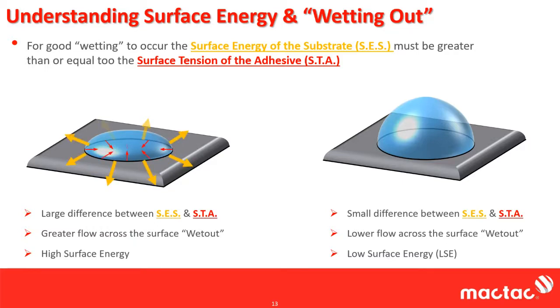On the right, then, we have an example where the surface tension of the adhesive is much greater than the surface energy of the material fighting to hold it, or I'm sorry, I'm saying this in reverse. The surface tension of the adhesive is really holding the bead together much stronger than what the surface energy of the material is trying to stretch it out. In this case, there's a much smaller difference between the surface energy of the substrate and the surface tension of the adhesive. What that results in is a lower flow across the surface, or you don't get as much wet out. And this is what we call low surface energy, or LSE for short.